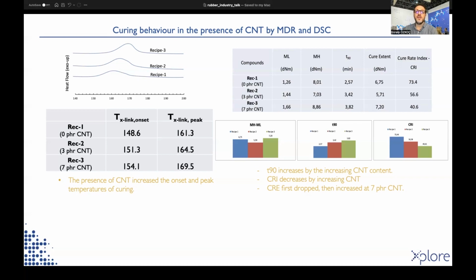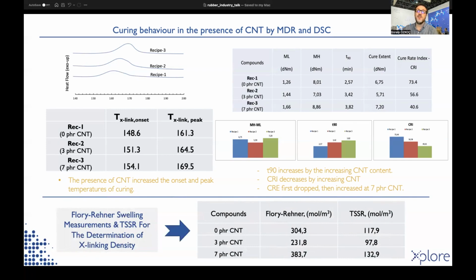In addition, cross-linking density first dropped by the addition of carbon nanotubes, but then increased at 7%. T90 values increased by the increase in carbon nanotube content. This can be due to the barrier effect of carbon nanotube against the diffusion of the chemical species that are involved in cross-linking reaction. However, if enough time is given, one could obtain a fully cross-linked structure. Similar to that, cure rate extent, which is associated with the cross-link density, first dropped, then increased at 7 PHR carbon nanotube content. This was also supported by Flory-Rehner swelling measurements and TSSR measurements.